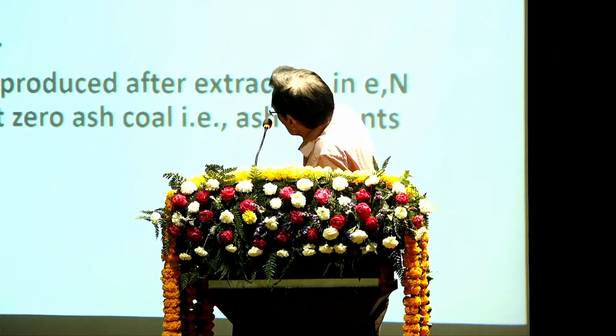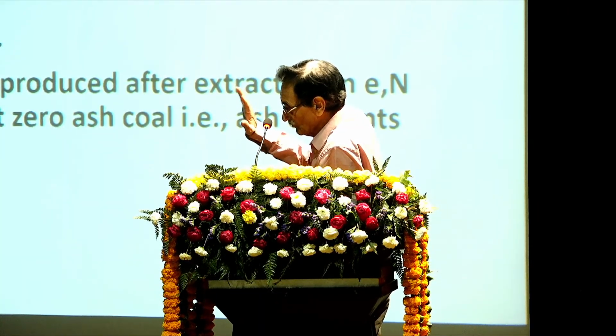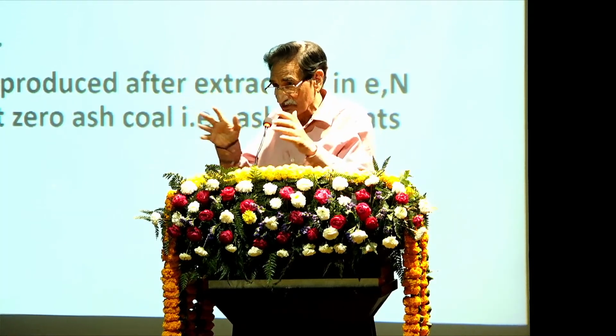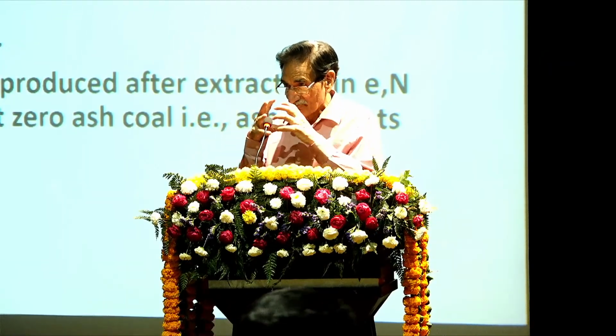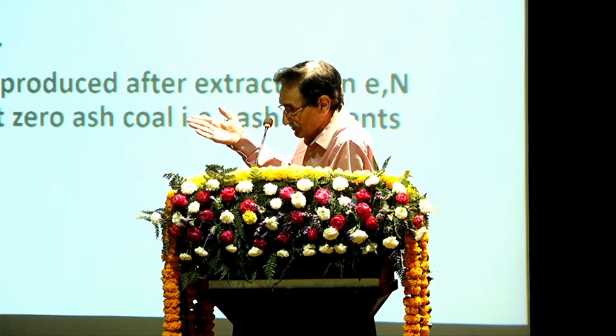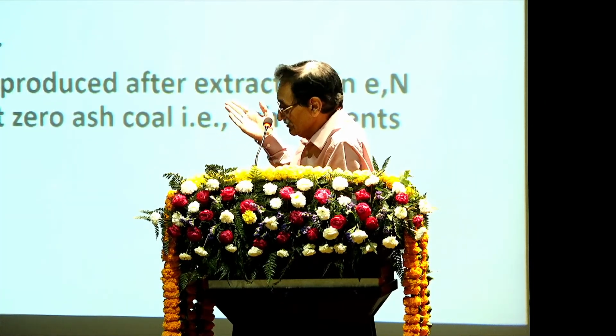Then we used binary solvents: N-methyl pyrrolidone followed by ethylene diamine, anthracene oil followed by N-methyl pyrrolidone, and anthracene oil followed by liquid paraffin. We could get extraction yield up to 25 to 30%, which was also not good. But then we thought of doing some other trick. We thought of working on the physical chemistry of coal, how to break the weak linkages, the physical attractions in coal. So we thought of using N-methyl pyrrolidone as the main solvent, which is well known and used in petroleum refineries, and breaking these weak bonds by using ethylene diamine or monoethanolamine, and we were very successful.